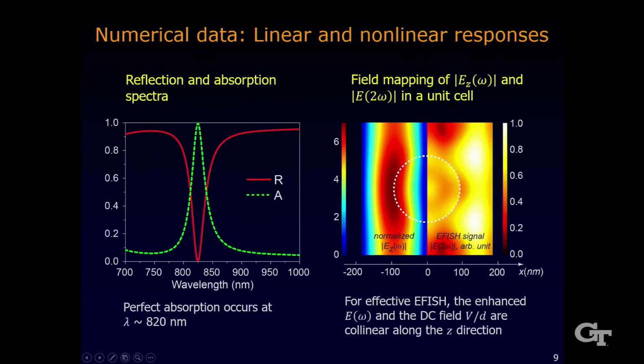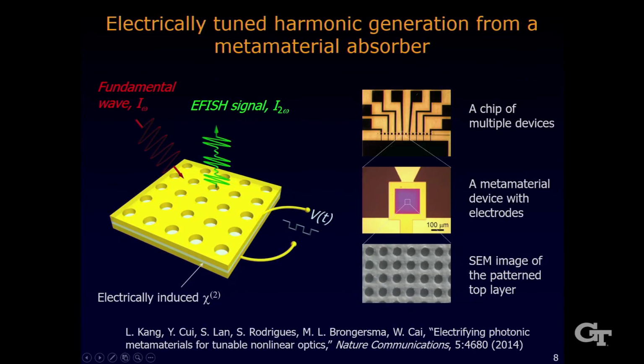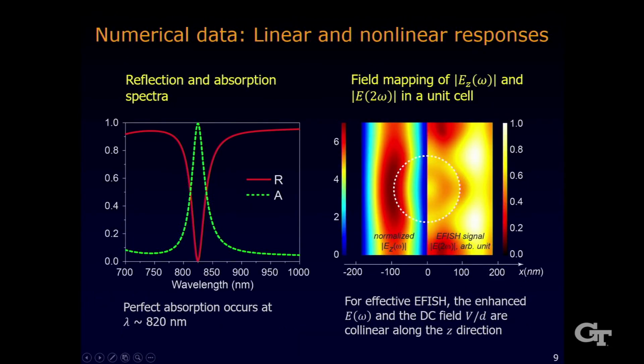Okay, so the metamaterial absorber is designed to have a perfect absorption band at around 820 nanometer, which is the center of our Ti:Sapphire laser. And from the simulation, you can see light is substantially enhanced in the cavity, by almost two orders of magnitude in terms of the intensity. In terms of field, it's one order of magnitude. You square that, it's two orders of magnitude.